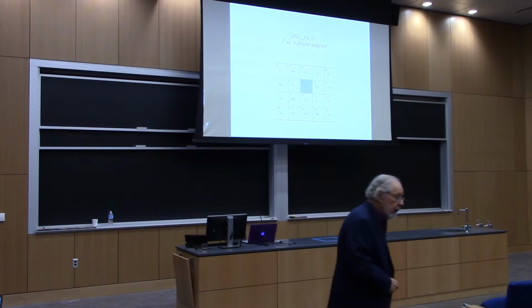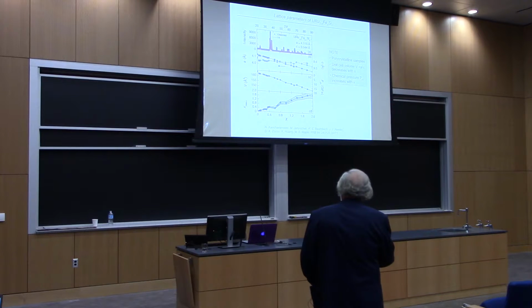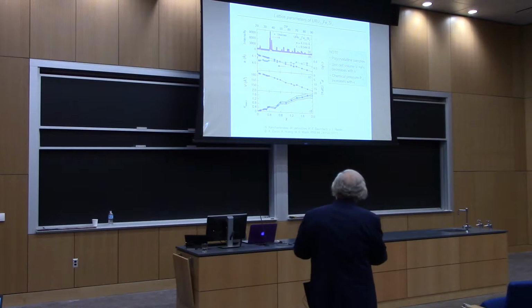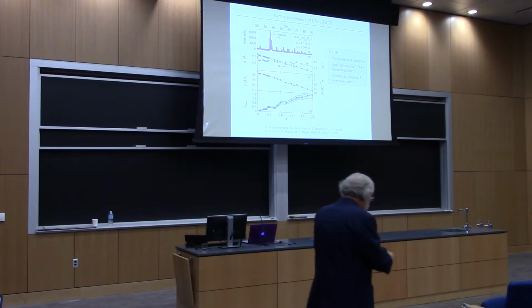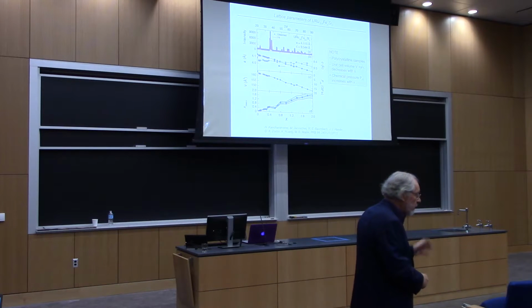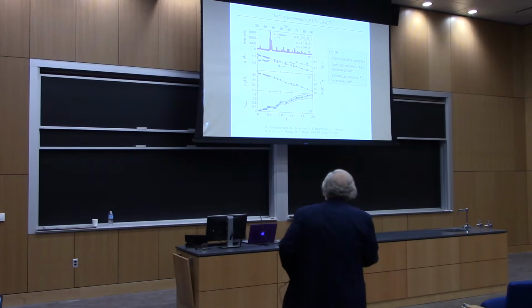So now let me turn to the iron substitution. We're going to substitute iron for ruthenium. That is going to decrease the unit cell volume, as I mentioned, and that's shown here. This is work on polycrystalline samples. This is exploratory work in the beginning, so it's much easier to work with polycrystals, and then single crystals come later. This is the a lattice parameter and the c lattice parameter. You see that c doesn't change very much. a decreases, and so the unit cell volume decreases as shown here between 0 and 2 for this value of x.